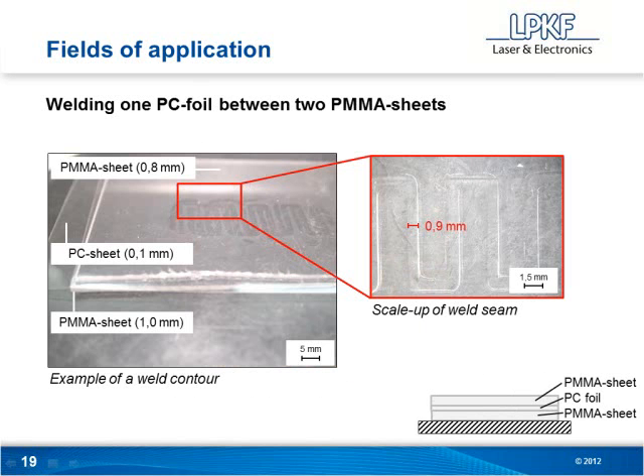Here's one where we have PC foil, so a relatively flexible foil, with two PMMA sheets above and below it. So all different thicknesses, and these are all weldable together. Again, the volumetric heating effect that you see with this type of laser welding. You can see a scaled up view of that, nice, very clean weld seams. It looks really good. You can't tell a huge difference between the clarity of the seam and the plastic itself. So again, aesthetically, it's a very pleasing weld seam.